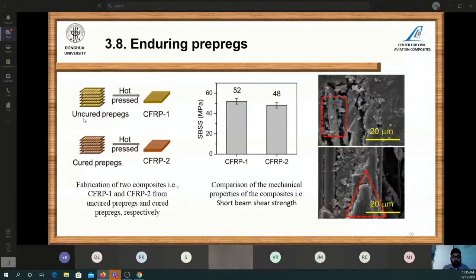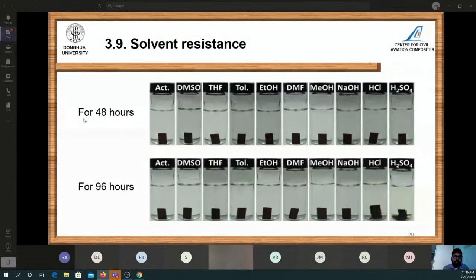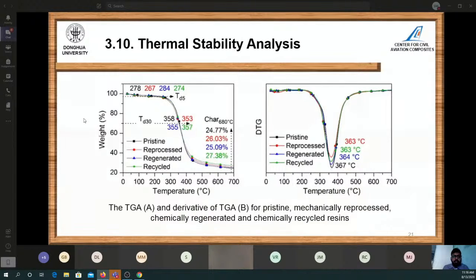These were the two types of composite coupon. One was from uncured prepregs, and the second one was from cured prepregs, and we got almost similar interlaminar shear strength. This resin also had good solvent resistance, and we can see that it lasted for 96 hours in different solutions, including acid and alkali. So it has very good solvent resistance as well, and also very good thermal stability.